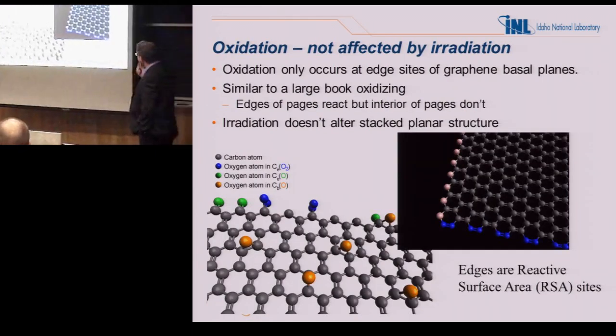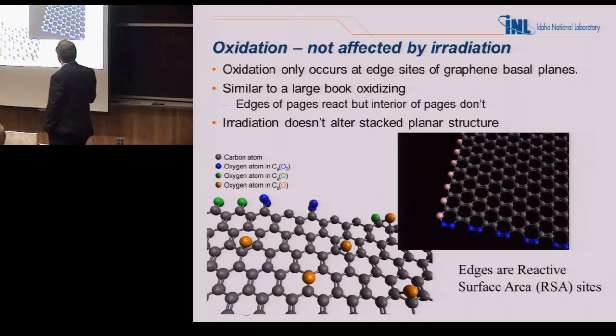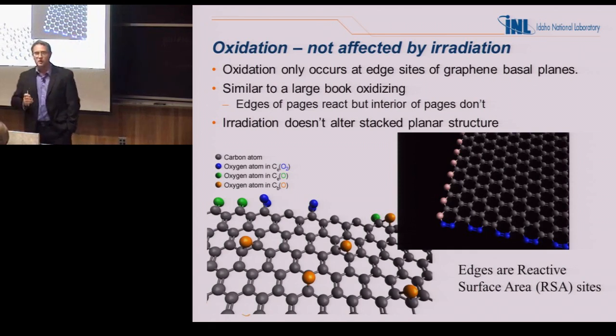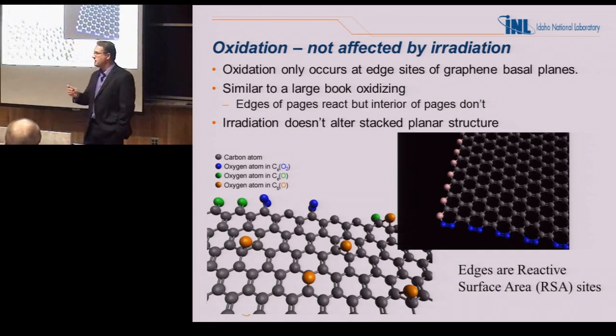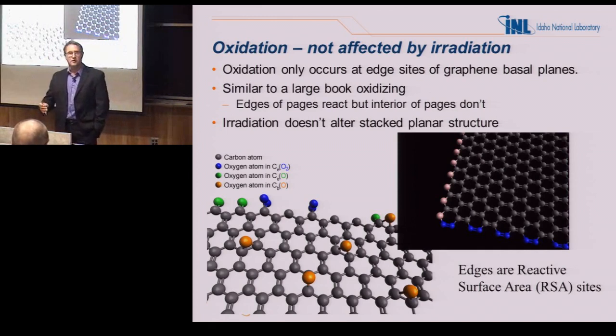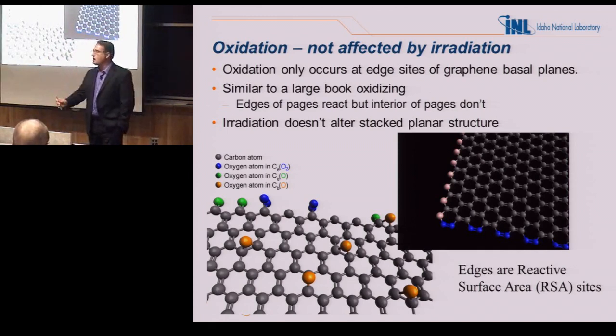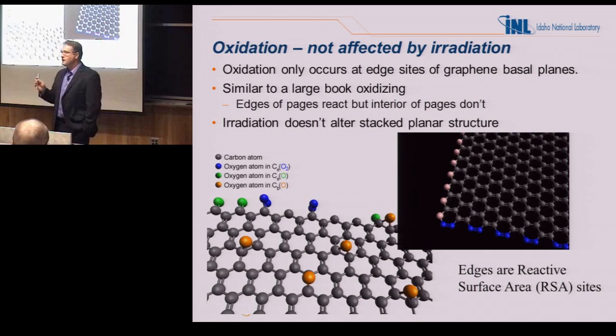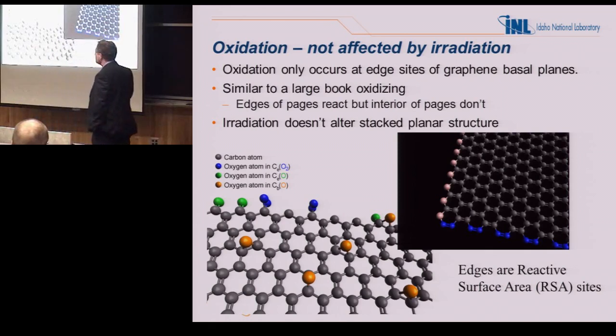Oxygen. Some of you will, I hope, like this slide. It's the last one. Basically, oxygen is not really affected by the irradiation. Oxidation only occurs on the reactive surface area sites on the edge of the graphene planes. It does not happen in the middle. So as a consequence, graphite does not burn. If there's one thing I want everybody to go out of this room with, is that nuclear graphite does not burn. It's not charcoal. There's no barbecues. Nothing can happen. It is like a large book.